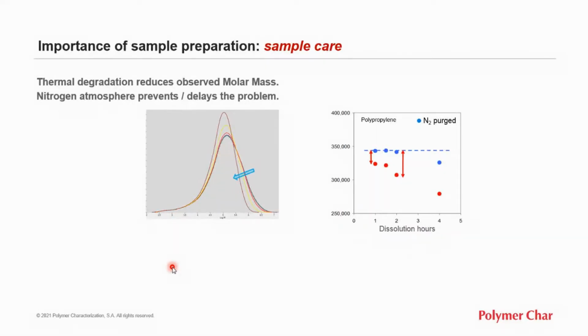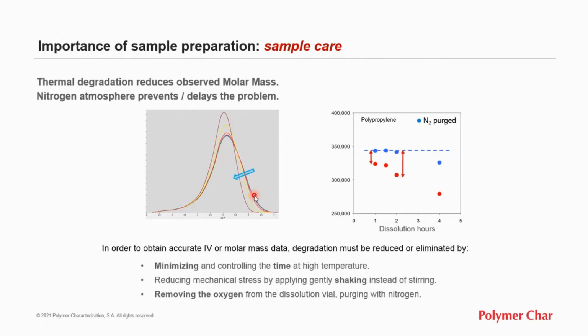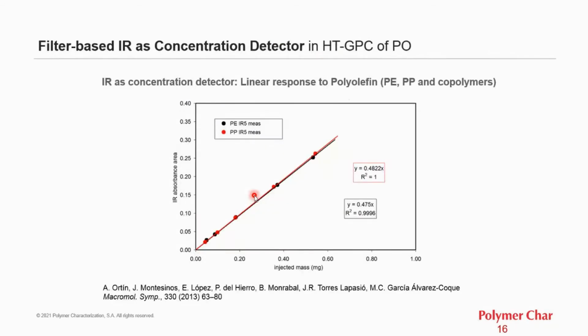In sample preparation dissolution, attention must be paid to thermal degradation. That thermal degradation reduces the observed molar mass and shifts the molar mass distribution, as we can see in the graph. We know that having an inert nitrogen atmosphere in the dissolution vial, this problem is delayed. It is also important to control the time spent at high temperature, reducing the mechanical stress, applying gentle shaking instead of stir bars, and also removing the oxygen during dissolution by means of a nitrogen purge, as I said. We apply all those features in the instruments.